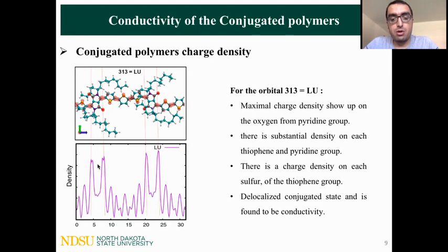Again, for the LUMO orbital, the maximum charge density here is on the oxygen from each pyridine group. Similar to HOMO, there is a substantial density on each thiophene and also pyridine group. So this charge density on each sulfur and thiophene group, being uniformly distributed, means that this delocalized conjugated state is also conductive. Next, please.